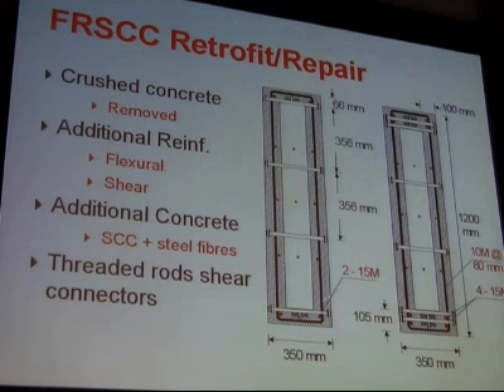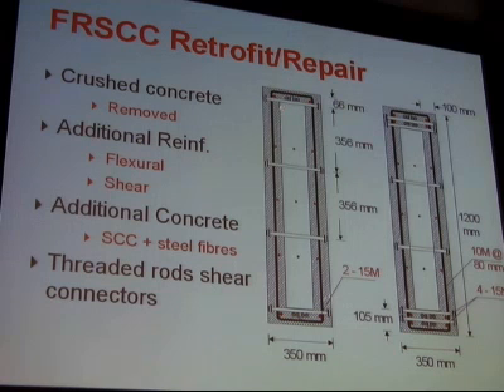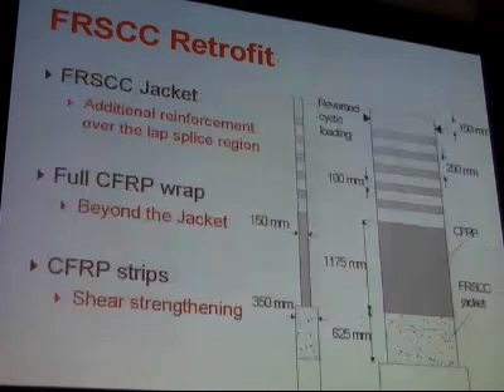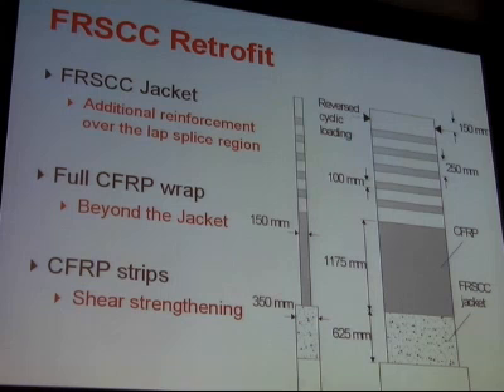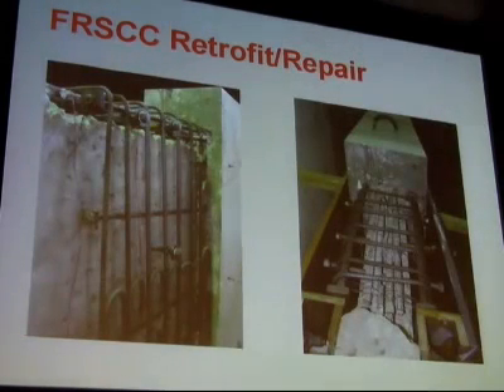In terms of the retrofit, it's quite a serious job. It involves removing some concrete at both ends, putting hoops around this area here, and not lengthening the wall, however, because this is removed concrete that's being replaced with the fiber-reinforced self-consolidating concrete. And we have through bars, which give the shear connection as well, and we have longitudinal reinforcement, which increases the flexural strength to make this a capacity-protected zone. So that's what it looked like, and a photograph of the retrofit here.